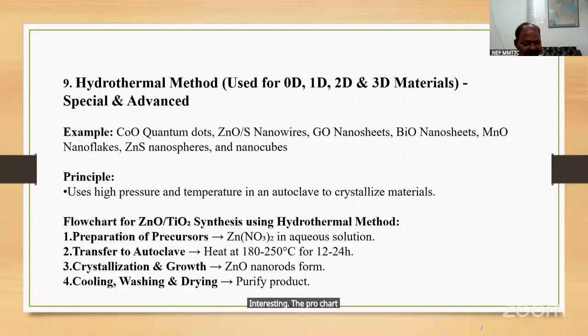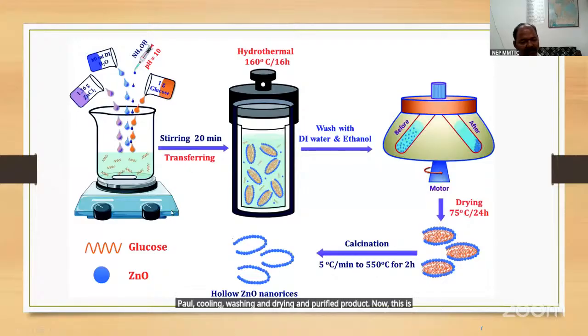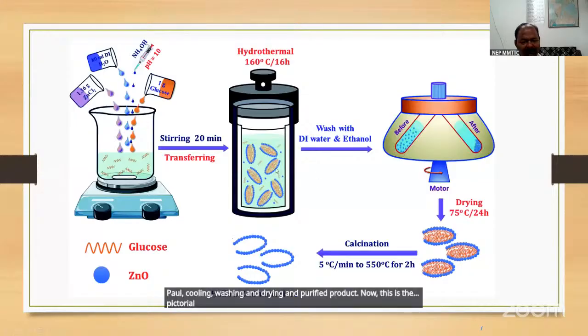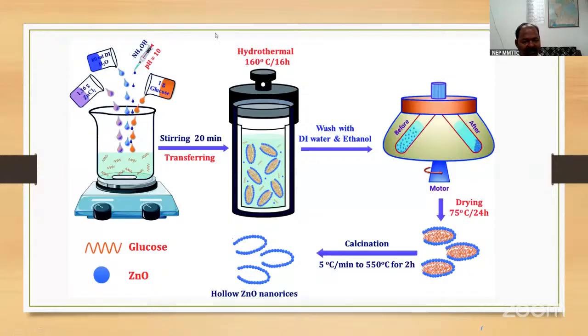The flowchart of this is given here. Now, the flowchart for zinc oxide, titanium oxide synthesis using the hydrothermal method. Preparation of precursors, zinc nitrate in aqueous solution, transfer to autoclave, that is, heat at 180 to 250 degrees Celsius for 12 to 24 hours, crystallization and growth, zinc oxide nanorods form, cooling, washing and drying, and purified product. Now this is the pictorial diagram of this one, stirring this, and now this is this one.